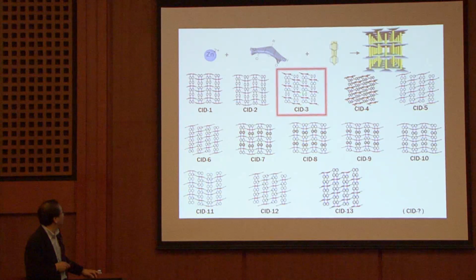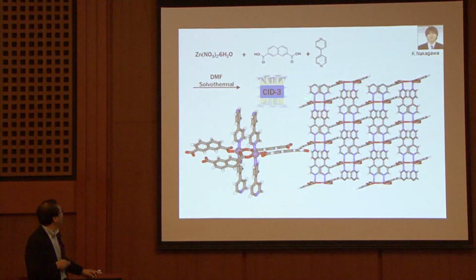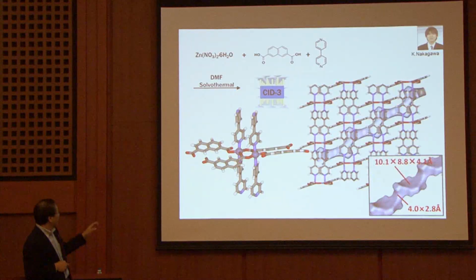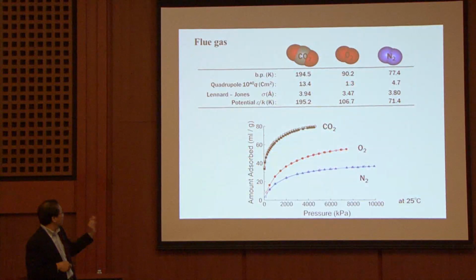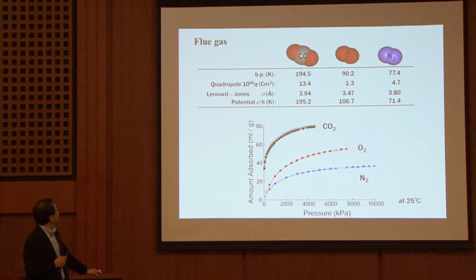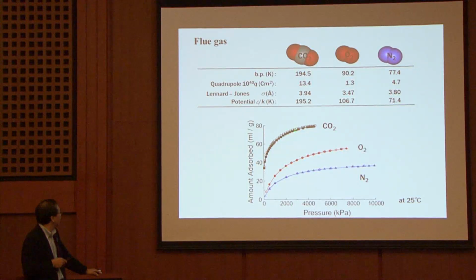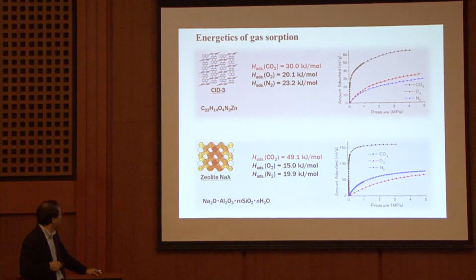And please look at this one, CID3. The naphthalene substituent is used for the structure here, and there are small channels here right now. And this is just a single gas absorption profile, N2, O2, CO2. It's not so good because the difference is not large. Okay? When we compare the zeolite capacity, this is the champion, NaX. This shows very sharp adsorption for the CO2.